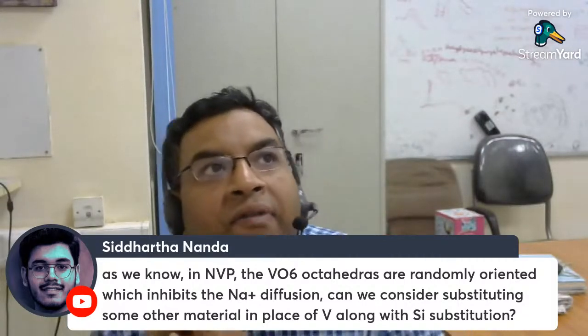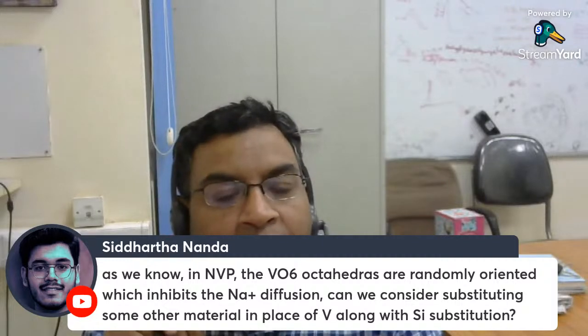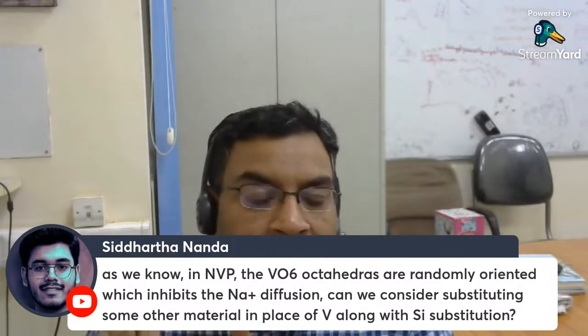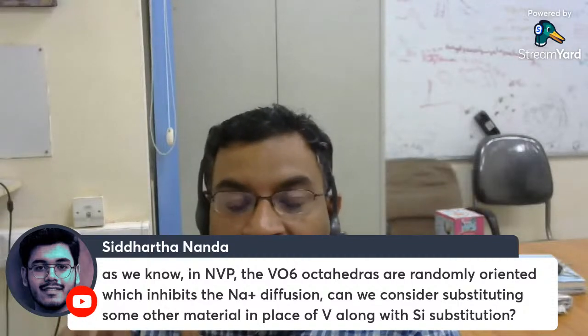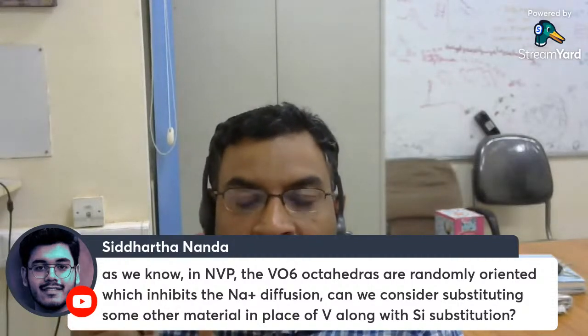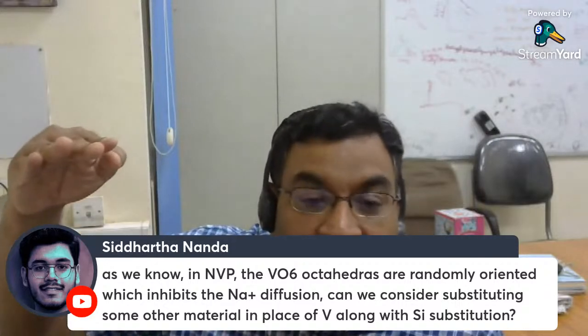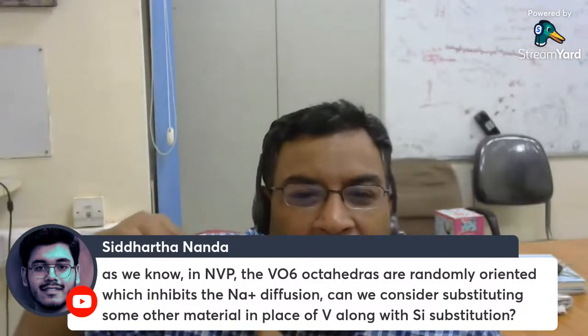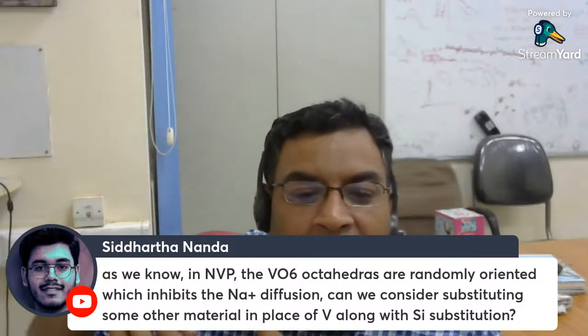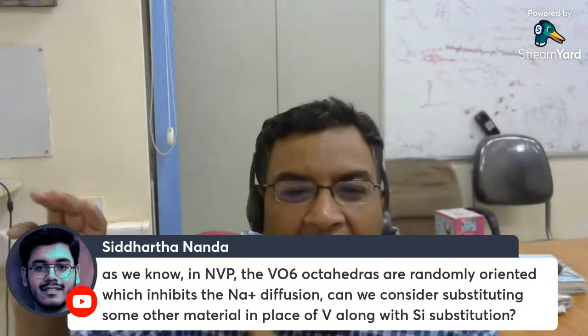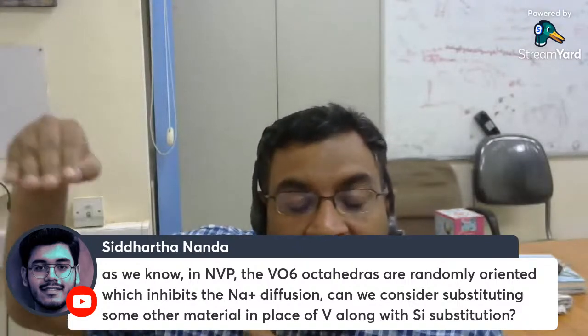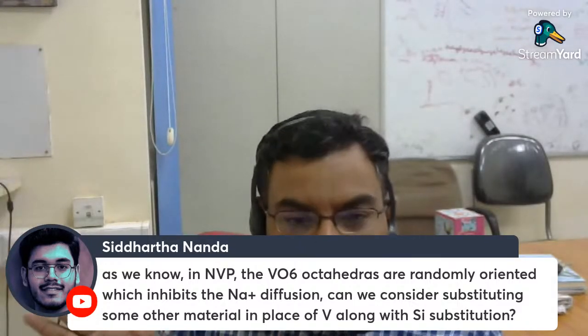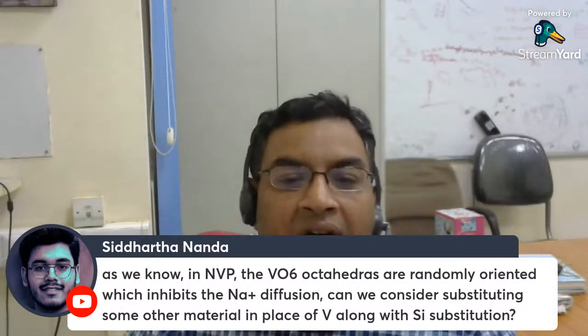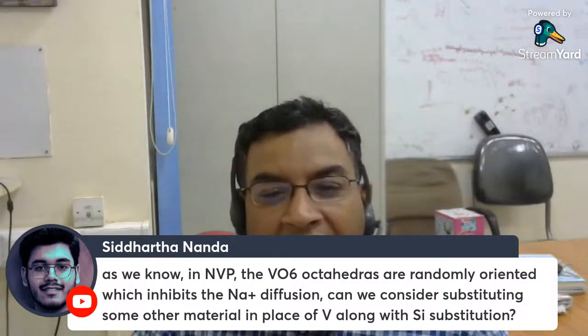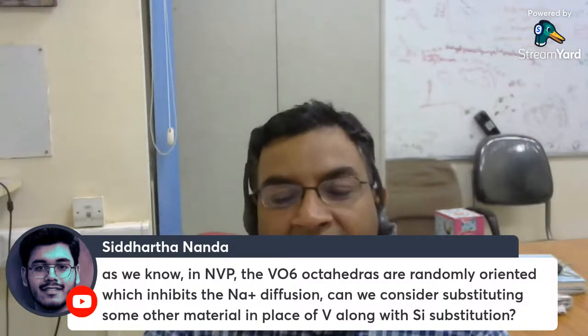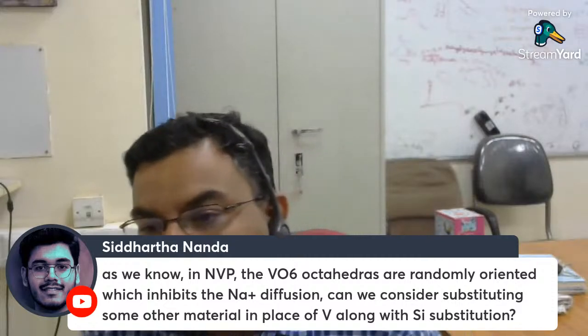But you know what? In vanadium, we are exploiting the V3 and V4 redox couple. So we have to use some element which is also a redox couple. That can either increase the potential, because V3/V4 occurs at 3.4 volts, and if you add manganese or another transition metal, they have their own redox couple, which will occur at some other voltage. So there are a few reports where they try to improve the potential of the battery cell by substituting vanadium along with the silicon substitution. But you can do that, of course.